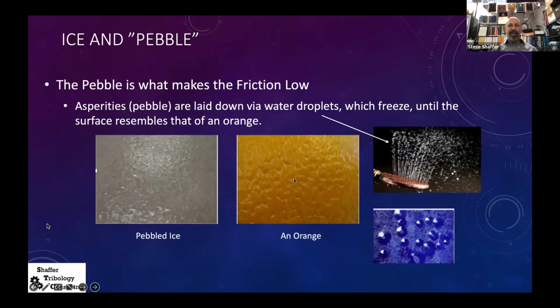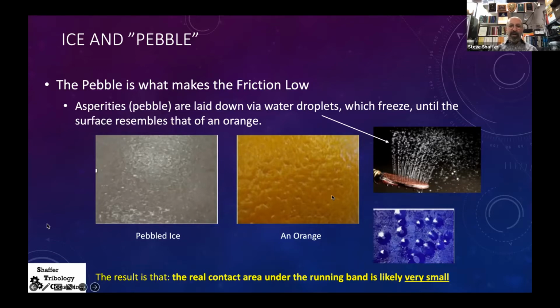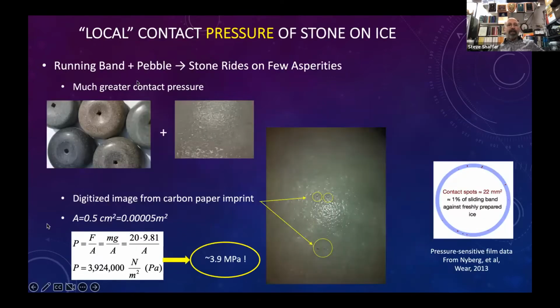And the result of that is that the real area of contact under the running band is likely very small, because we're only sitting on bits of pebble on bits of running band. So let's recalculate now. If we take the running band and the pebble, the stone's riding on just a few of the asperities, it's a much greater contact pressure. We did some measurements at Battelle. This is pretty easy. We took some carbon paper, put a stone down on it on top of the ice, and then we got a picture of it and digitized that. And we ended up with an area